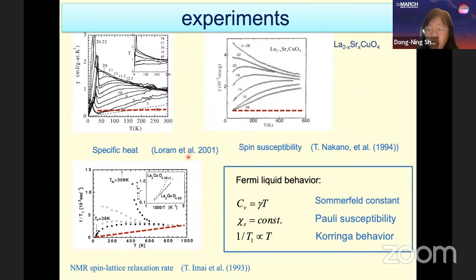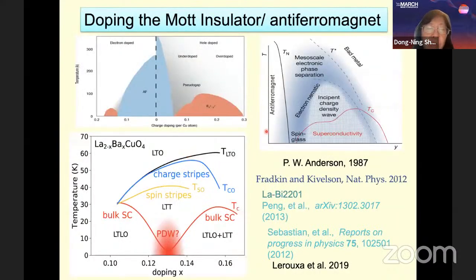Those indicate our system is quite different from the pairing of Fermi-liquids. The starting point, first proposed by Phil Anderson, is from the strongly correlated point of view, doping the Mott insulator with antiferromagnetic order. Other experimental evidence supporting this picture is the observation of antiferromagnetic order at low doping, and the pseudogap above the superconducting critical temperature, as well as charge density and spin density waves above the superconducting temperature.